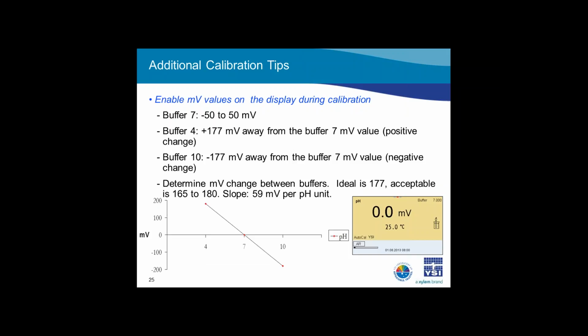Next, make sure you are looking at the pH millivolts during calibration. Again, the pH millivolt value is the raw signal coming from the sensor that the instrument converts into pH units. Evaluating the millivolt value during calibration can help us document sensor aging and help us to determine if the sensor needs serviced, cleaned, or replaced. Evaluating the millivolt values will also tell us how good our calibration is or if we're nearing the outer edge of the acceptable limits. This can help us plan for future maintenance or replacement requirements.